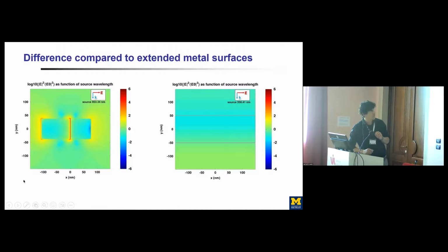So here I show, again, the same collection of two silver nanoparticles. We are computing the value of that electric field. And here we have an extended silver bulk, basically a single crystal of silver under the same conditions. And you see that there's no enhancement in the electric field. So for all intents and purposes, as I said earlier, the light energy is concentrated at the surface of these nanoparticles of silver under these conditions.